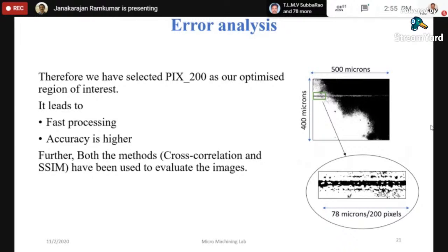So hence, both the methods, cross correlation and SSIM, have been used to evaluate the image, and this evaluated image will be given back to the system. If I convert this 200 pixels into microns, it is 78 microns. Our focus was to develop more on microns. We did not try to focus on nanometers because we had a limitation of the wavelength of the laser. We had a limitation, so we did it with microns.